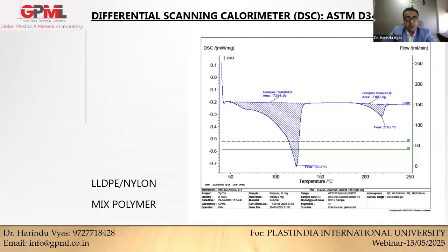But the test that I told earlier, that is FTIR, says that this material is polyethylene, but I don't know which polyethylene. So I did DSC and found that it is an LLDPE because it has a melting point at 123. If it was LDPE, then we know that LDPE melts at 90 to 100. We know that LLDPE melts at 120 to 125. Suppose the melting point has increased and is above 130, then we will find that it is HDPE. Now the melting point at 218, which material is that?